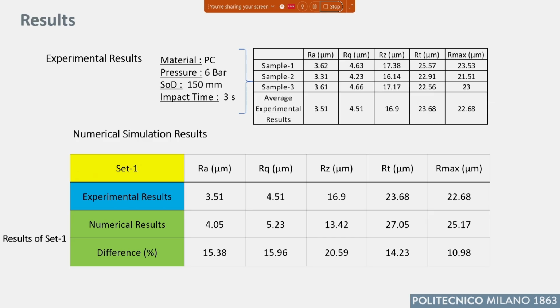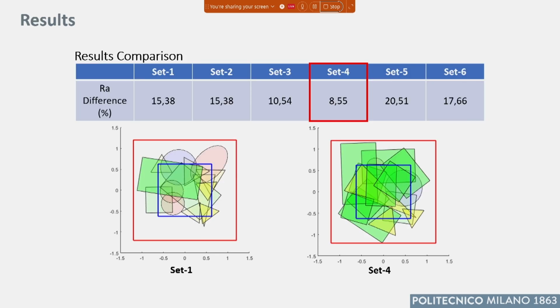Okay, and this is indeed the same result in a table. These are the experimental ones, and we see, to summarize, the result of set 1. So we have that the difference is between 10% and 20%, let's say. So we consider this result as satisfactory. There are other sets, other combinations of impact that were also considered, and the difference of Ra in this case, the minimum one, is something less than 8%. But anyway, whatever the set that we are considering for impact, in the end the trend remained the same, between 10 and 20%.